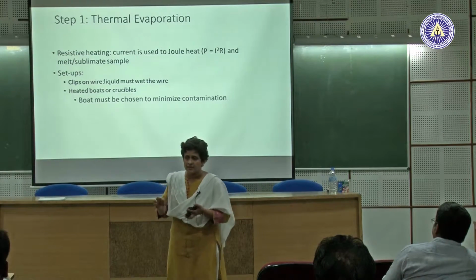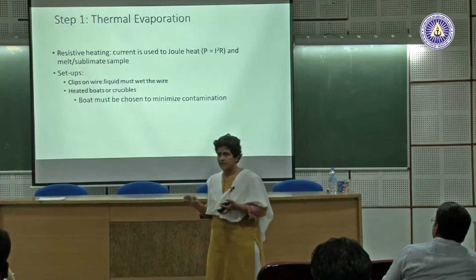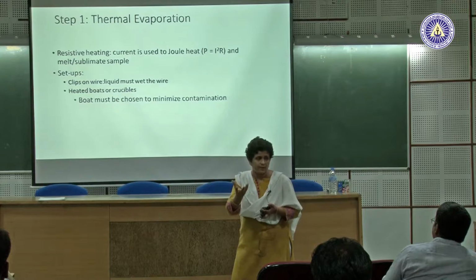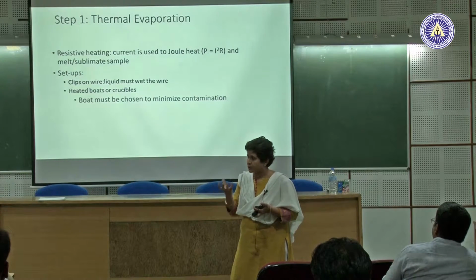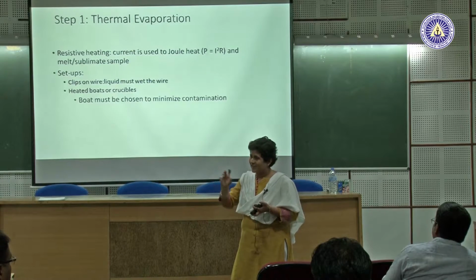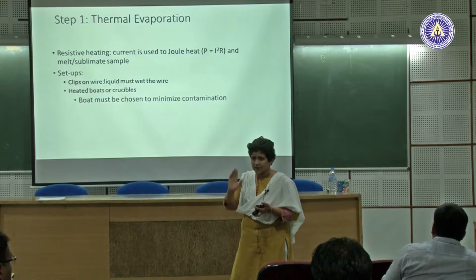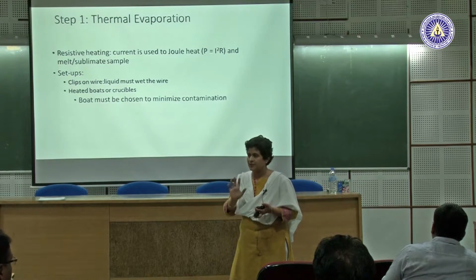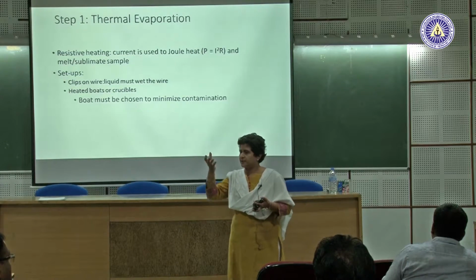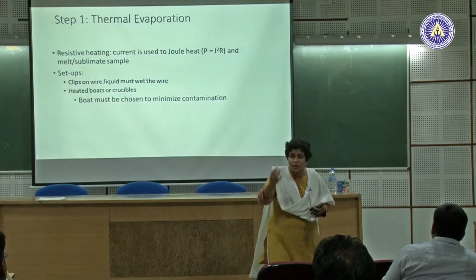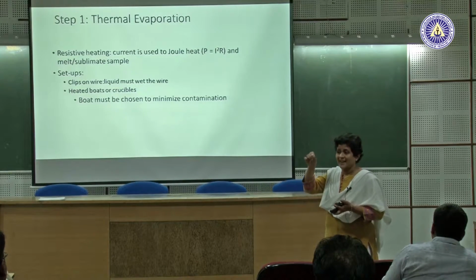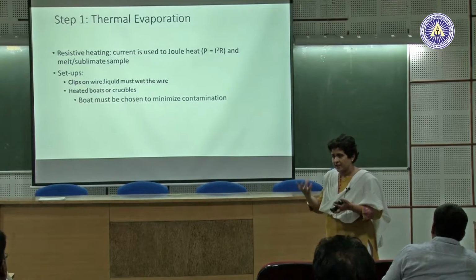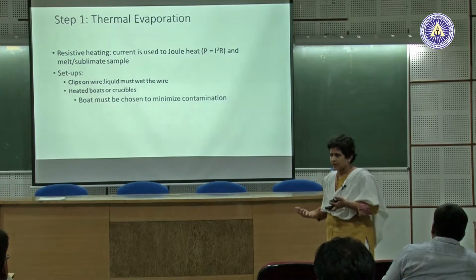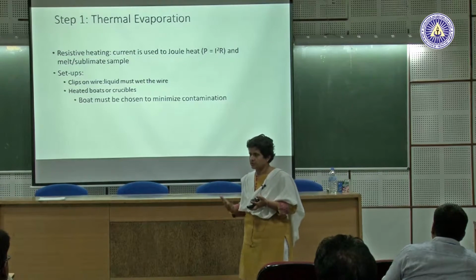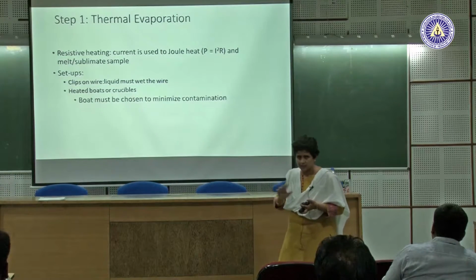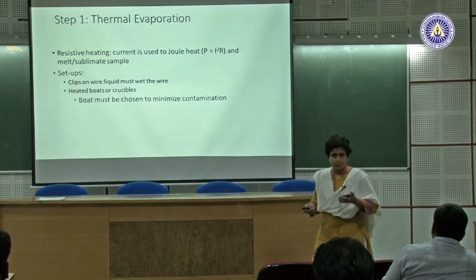And the techniques like molecular beam epitaxy come from all the technology that goes into creating that source where you can control the deposition rate. You control the temperature within 0.1 degree centigrade or so, so that the flux that is coming out is very well controlled, and that's basically technology. So just evaporating something and getting a deposition is one case. The second is having a control so that I know that I am depositing 1 angstrom per minute, for example, in which case I need to control my source. And today there are techniques and tools which people have developed that can give you that kind of control, and that's completely in the manufacturing regime, how you manage that control.